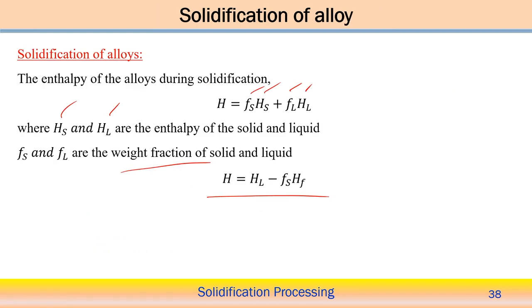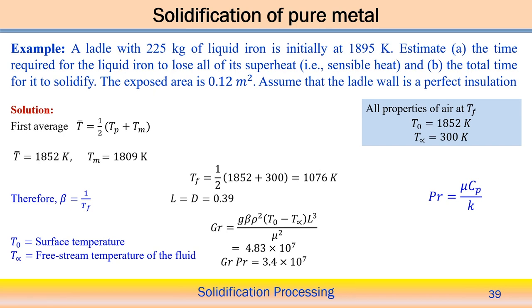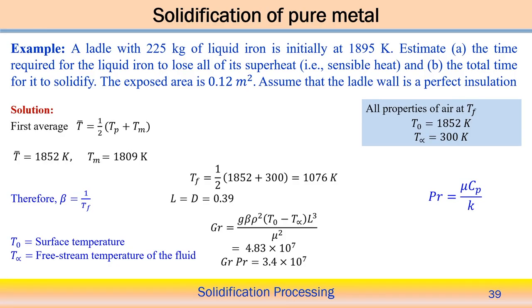I am not going into much detail about the solidification of alloys; maybe in a further advanced course this can be considered. Now, we can take an example of the solidification of a pure metal, to understand how to implement the different temperatures to estimate the heat transfer coefficient and to calculate more precisely the solidification time for a pure metal. Here we consider a ladle with 225 kg of liquid iron initially at 1895 Kelvin. The melting point temperature TM of the iron equals 1809 Kelvin. So 1895 Kelvin is above the melting point temperature, which means this iron has some superheat.